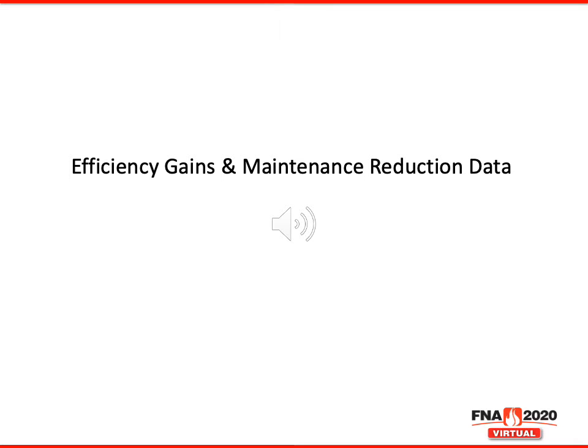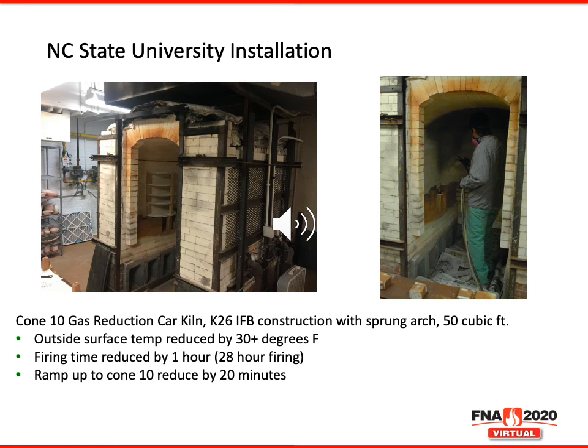Let us now take a look at the efficiency gains and the maintenance reductions achieved when the coatings are properly installed. At North Carolina State University's ceramic department, their clay studio utilizes a Cone 10 gas reduction car kiln. The refractory construction consists of 2600 degree IFB with a sprung arch and 50 cubic feet of area. Utilizing the coatings at a thickness of approximately 3/16 of an inch on the hot face of the IFB, the outside surface temperature of the Cone 10 gas reduction kiln was reduced by 30 plus degrees. The firing time of the kiln was reduced by 1 hour and ramp up to Cone 10 reduced by 20 minutes.